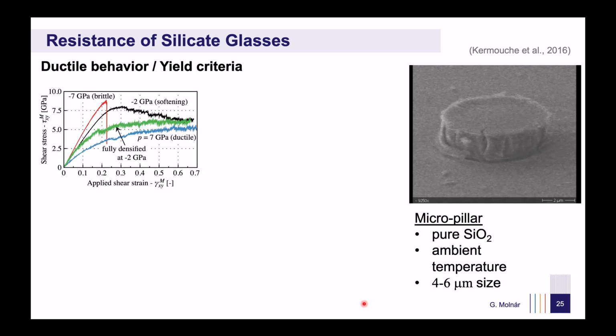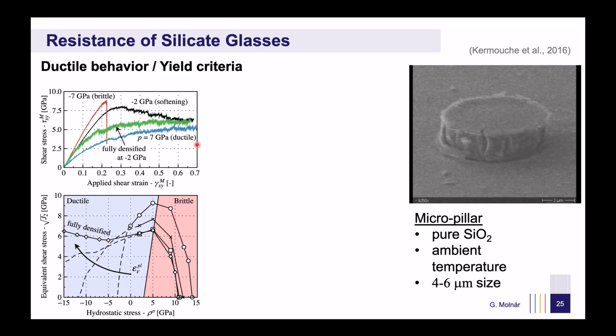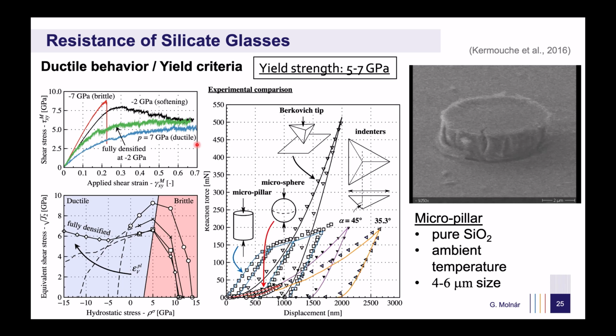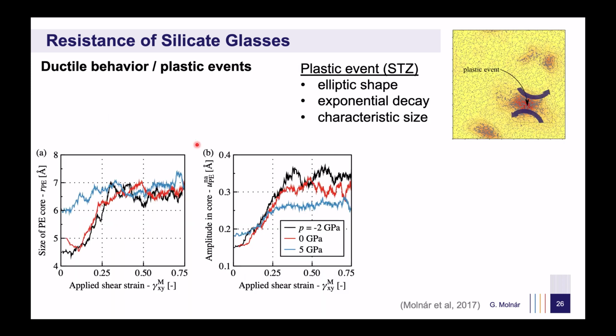Using molecular dynamics, we tested the material under different loading conditions, varying the pressure state, and identified 3 distinct responses: brittle failure, softening, and plastic deformation. These results allowed us to formulate a densification-dependent yield criterion, which we then calibrated against experimental data, ultimately identifying the yield strength of silica in the range of 5 to 7 gigapascals, a value much higher than those used in standard glass design.